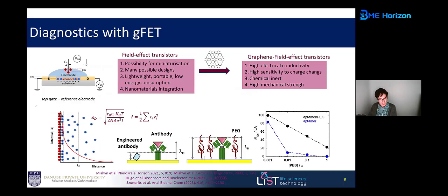So why is this a limitation? These limitations come from something related to the Debye length screening we have on this type of sensors. If you look at this lambda D, you see it is inversely proportional to the ionic strength. That means the larger the ionic strength, the smaller this LD value. And LD in very high ionic strength solution, like in full blood, would mean an LD of around 1 nanometer. So what that means is we can only measure very sensitively 1 nanometer away from the graphene surface.